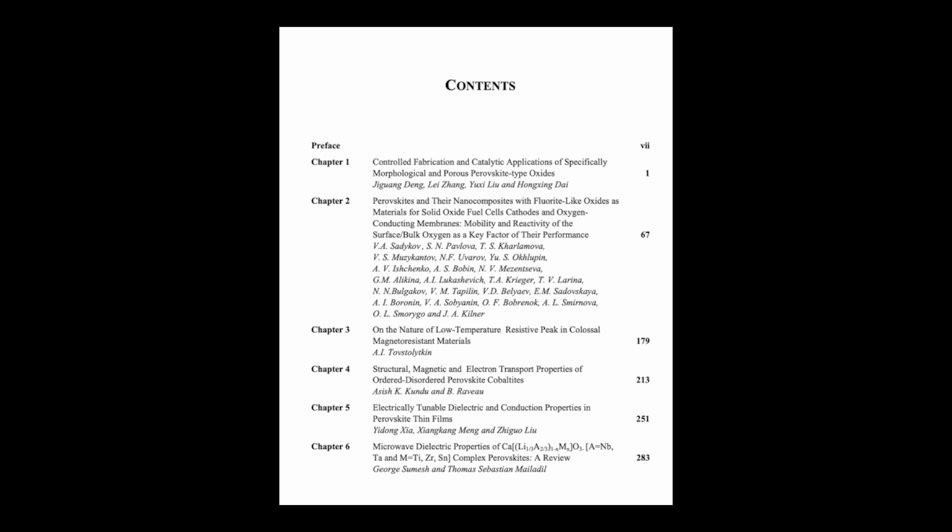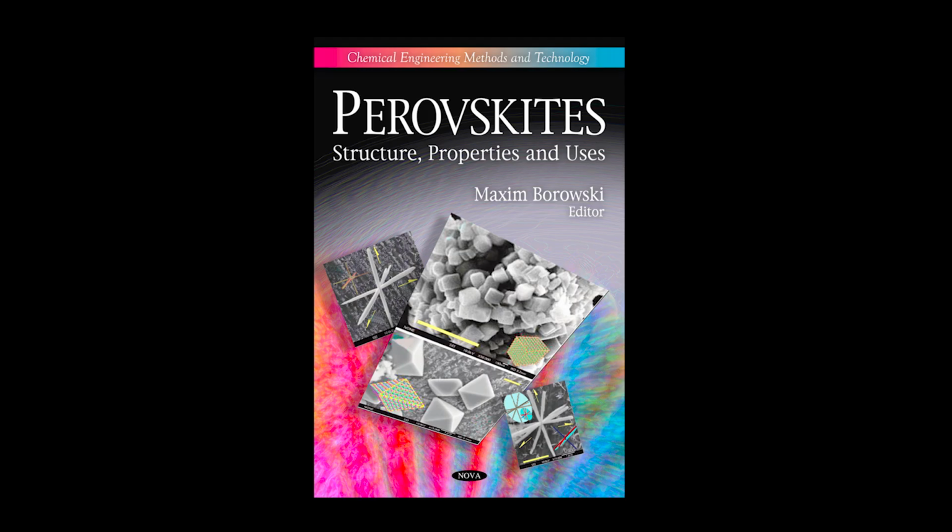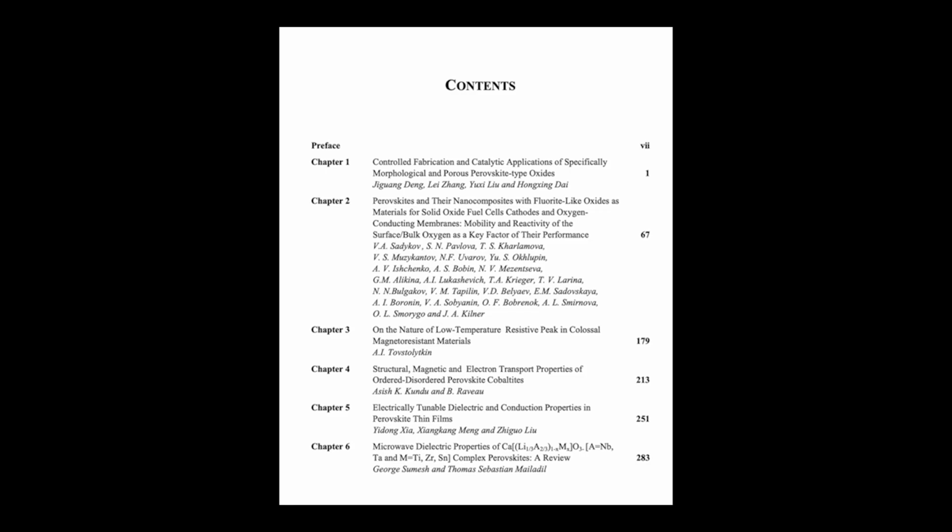The SO2 starts to react aggressively with the A-site cations, like La, and the lattice oxygen itself. This leads to irreversible structural destruction through the formation of stable, bulky, and non-catalytic sulfate compounds on the surface, like lanthanum sulfate, La2(SO4)3. While some partial regeneration might be possible by heating the catalyst under strongly reducing conditions, the underlying structural damage often means the catalyst performance is permanently compromised. So the challenge here is really engineering A-site cations or surface coatings that are intrinsically more resistant to sulfate formation without simultaneously poisoning the crucial redox activity happening at the B site. It's a tricky balancing act.